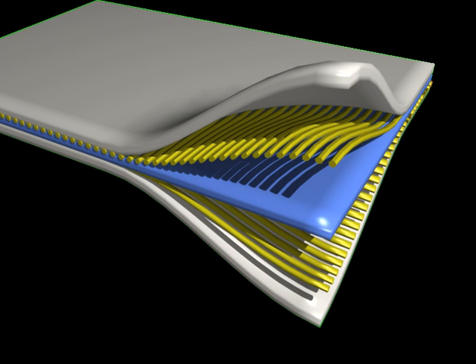Still, the tensile strength will be greater than for the purely perpendicular orientation, since the force perpendicular to the fibers will decrease by a factor of 1/sin θ and the area increases by a factor of 1/sin θ producing a composite tensile strength of σ_perp / sin^2 θ where σ_perp is the tensile strength of the composite with fibers aligned perpendicular to the applied force.